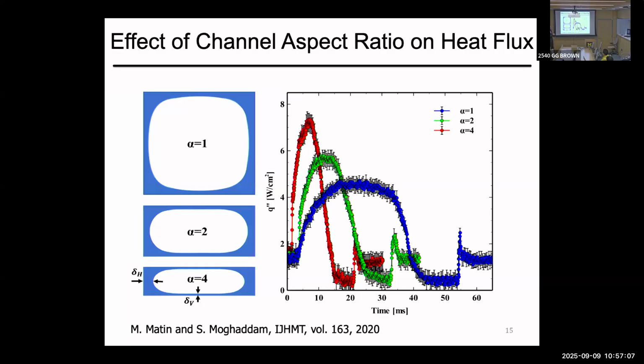Thinner films means a higher heat flux rapidly. But thin film also means a lesser amount of liquid, so when it evaporates, it very quickly dies down, whereas thick films give you less heat flux, but over an extended period of time. Right? So some of these things, when you measure and analyze, you say, oh, this makes sense, but it was not so obvious before the measurements.